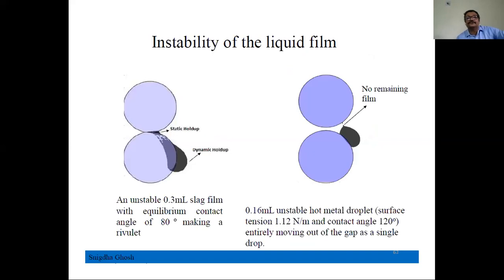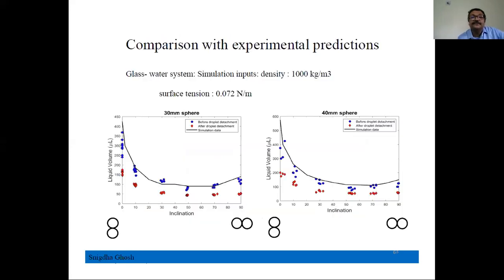Of course, this can be extended if I change the surface tension, for metal, slag, and so on. Depending on the contact angle, if it is not good, then it is not going to form a film like this, it is going to flow like this. Many fundamental things can be explored, but I'm just telling you how the techniques of mathematical modeling can be used. Then we did experiments at different orientations. This is vertical, then 10-degree angle, 30-degree angle, even up to horizontal. We measured experimentally the hold up, and whatever we predict using the model matches very well with what we found experimentally.